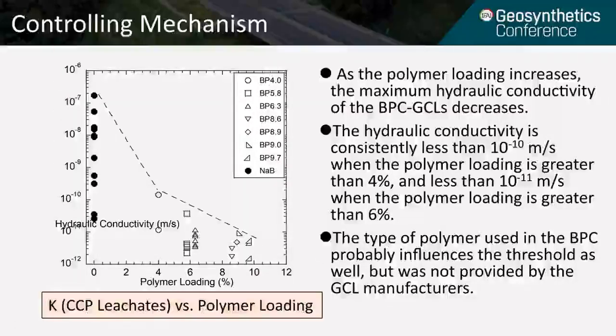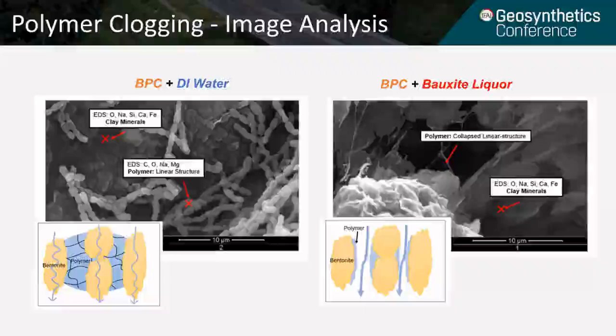Similarly, for the BPCs to CCP leachates, when the polymer loading is 5.8%, you will see the hydraulic conductivity is usually less than 3 times 10 to minus 11 meter per second. Also, I want to point out that at a similar polymer loading, you will see some differences in the hydraulic conductivity from this slide or the previous slide. So this is likely due to different permeation liquid or different types of the polymer that is in the BPCs. So far we know the polymer is playing a big role in this game.